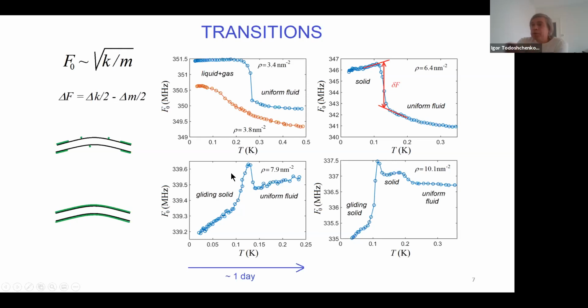So fine, but when we increase the density even higher, this additional stiffness due to the solid disappears, leaving only this peak, so that the solid trace can be continuously followed from the solid, which we call gliding solid, to the liquid. So this new solid phase has the same stiffness, or basically zero stiffness, like a fluid. We were really quite puzzled by this, but when we increased the density even further, new confirmation comes that at some point the stiffness appears by a jump, so that we enter from this mobile soft solid to the normal solid at these intermediate temperatures, which then melts to the uniform fluid.